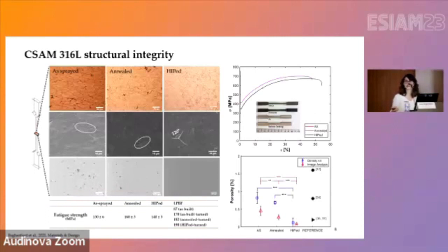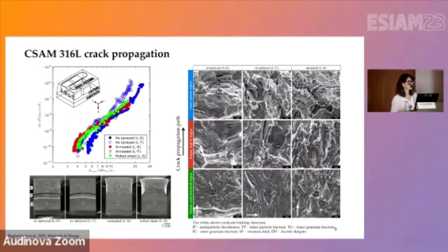And here are the results for the actual fatigue test of our samples, that are comparable and in line with laser powder bed fusion data that we could find in the literature with different process parameters. We have also performed, in collaboration with our colleagues in IPP in Prague, crack propagation tests on our samples, forcing the crack to propagate in different directions in order to see whether we have any anisotropy inside the cold spray samples. In as-sprayed condition, we have some anisotropy because the way the particles are packed affects the crack propagation. But after annealing, the results that we could get are very similar to the data for the rolled sheet, so very similar to bulk material that we can get with other additive manufacturing techniques.